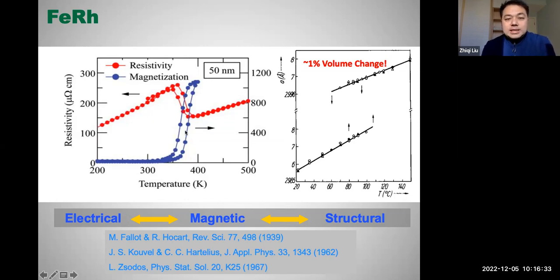So for this material, its lattice constant and its magnetization and also the resistivity are all strongly correlated. This phase transition, this metamagnetic transition, is a first order transition. When this transition occurs, the lattice constant has a sharp jump. And also because of the first order phase transition, it has a thermal hysteresis. When you try to warm up this material through the phase transition temperature and then cool down through the phase transition temperature, you get a hysteresis. So this would be an ideal material if you try to use the piezoelectric strain to modulate its lattice, and then its magnetization and its resistivity will all be changed.